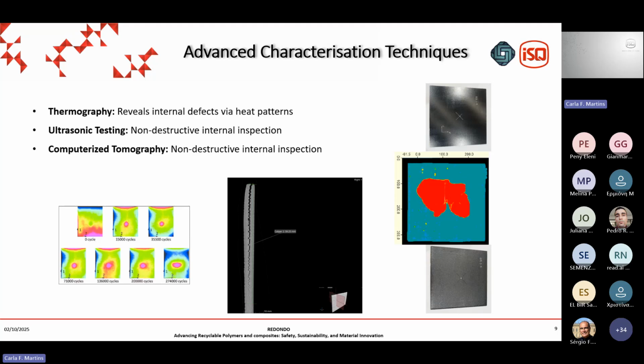Ultrasonics are also not a brand new technique, but in modern times, with the development of software and other analytical tools, we can access the interior of our material. So what we have here on the right-hand side is a panel that was tested in impacts, as we mentioned before. Before test, and at the bottom after test. You see that there is no visible damage on the surface of our specimen due to that impact, but an analysis with ultrasonic C-scan reveals that something like 1/3 of our specimen was completely damaged by interlayer delamination on the inside, and that is not entirely visible just with a visual observation.